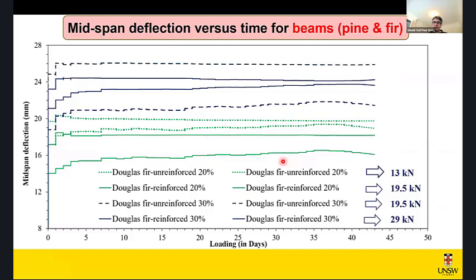Now, this is the midspan deflection versus loading. This is something I prepared around 2 weeks ago, so it was around 6 weeks into the loading. So the range of the loading, you see the load for the unreinforced one, the dotted line, is 13 kilonewton. When we add reinforcement to that one, 20% of that was 19.5 kilonewton, which is nearly 50% higher than this 13 kilonewton. All right, then that's the improvement.